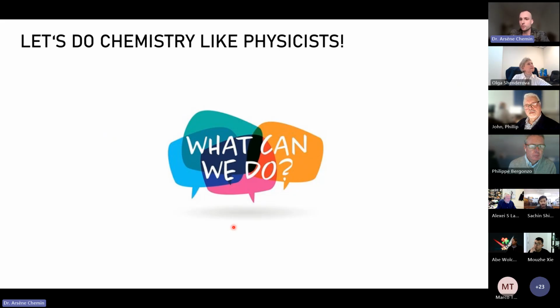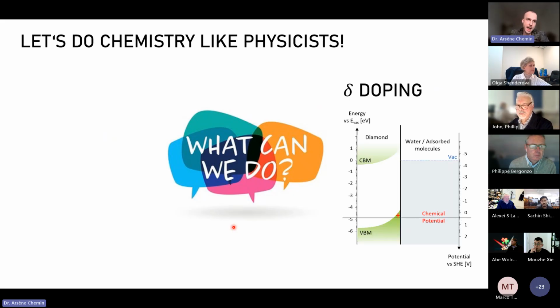So what we can do with this framework is, for instance, understand the surface delta doping. So many of you understood that H-terminated diamond is actually conductive at the surface, even if it's not doped. To be frank, when I started working with diamond and people tried to explain that to me, I had a very hard time understanding what was happening there. And what was happening is actually rather simple. When you have the equilibration between the Fermi level of the diamond and some adsorbed molecules like water, you will have a band bending which is so strong that it will cross the Fermi level of the system. And this will lead to holes in the valence band at the surface of the diamond, and this basically behaves like a metal. So this is how we can very easily understand delta doping.